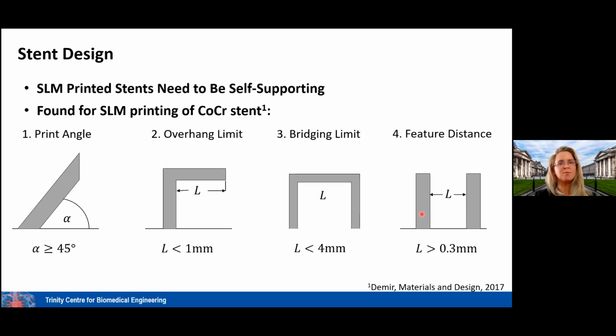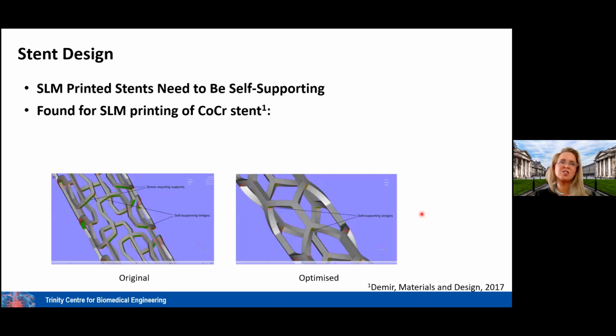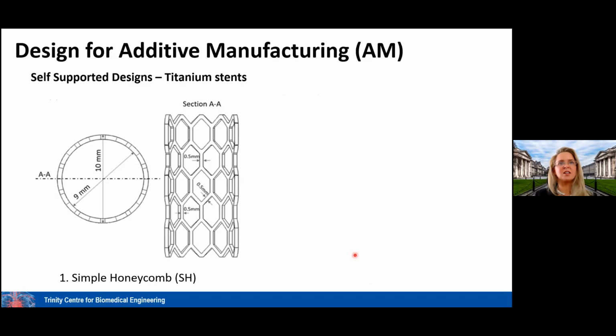So considering these types of constraints on the selective laser melting process for printing stents, we can see that maybe a design such as that on the left, which is typical of a more complex stent design, is not really achievable because it's not self-supporting. It has overhangs that are very long. So you can see here, these would be the overhangs when it's printing in this direction. We would have these overhangs, and that wouldn't work. So we have to print something more like this, a honeycomb type structure, because we keep everything there at angles of 45 degrees or greater. So knowing this, we said, okay, let's try and design some stents for additive manufacturing.